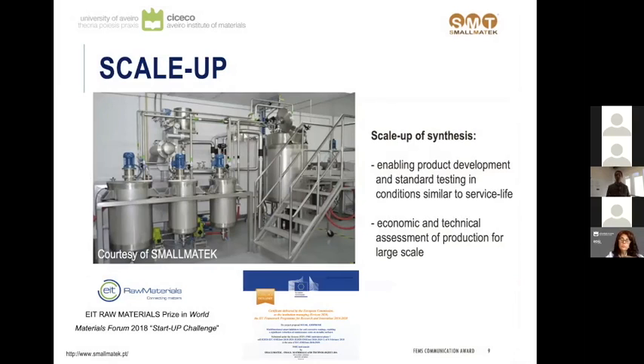promising nanocontainers for corrosion protection, but we couldn't find an industrial partner to produce these materials for coating developments. So we decided to create a company to do this business, so to basically upscale the most promising technologies that we were developing in the lab at the University of Aveiro. And the photograph you see here is actually the first industrial unit from the company, which is able to upscale the synthesis of one of the materials we are talking about from, let's say, 10 grams per batch to 50 kilograms in dry content.